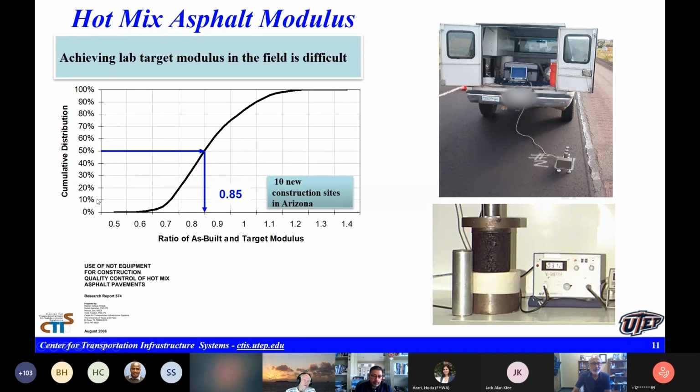So one of the things, for instance, we found for a project in Arizona, you can look at the 10 different new construction sites, and you see that the target that you get from the laboratory testing is very difficult for a conscientious contractor to come up with. So on average, they can give you 85% of what you get from the briquettes that you prepare.